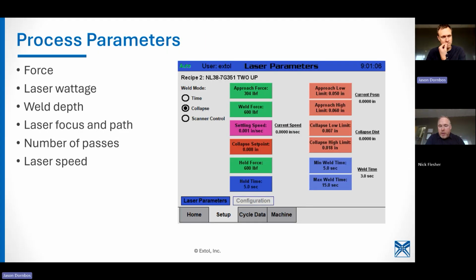Just to touch on process controls quickly, we essentially have force, laser weld depth, laser weld wattage, how focused is the beam, what's the path, number of passes, laser speed. I would say 90% of the time we weld on collapse, meaning you set how deep you want that weld to go. The machine takes basically a datum, says, all right, I've hit a pre-weld position. We actually have settling speed because what we found is some plastics would just kind of continue to collapse. So we wait, make sure we get to a spot we want to actually say, okay, zero the position. Apply the laser energy while it's collapsing.